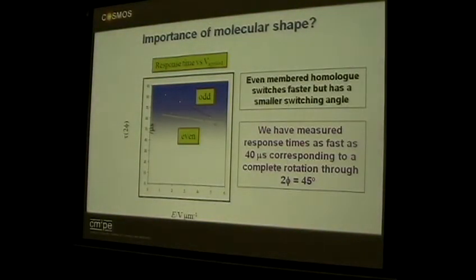At the same time, you do get odd-even effects in the response time. But still, less than 80 microseconds. That's the time for the double switch, from minus E to plus E, from minus tilt to plus tilt. Still less than 100 microseconds.